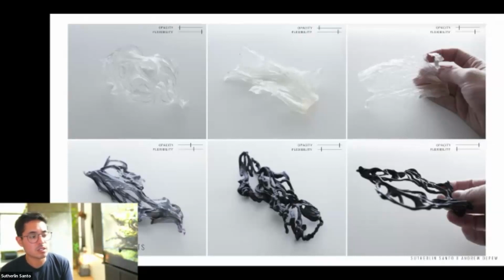And I guess one thing we also didn't mention was that part of the reason we put non-stick baking sheets on the list was because you can extrude onto those non-stick baking sheets or onto a silicone mat, put it in your oven at a low temperature, and that way you can help dehydrate the sample if you don't have a dehydrator or you don't have the time to let it sit out for a while. But as the water evaporates, in general, especially with this formula, mass is actually evaporating.